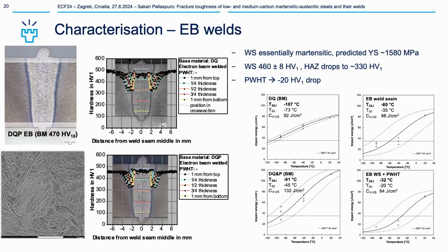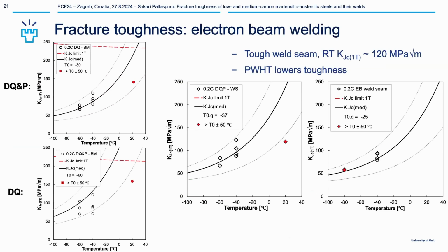Also for these electron beam welded materials, with environmental effects excluded, we see that properties are fairly in level with the hardness of the base material. So we achieved that there. Low mismatch, that's good. And there's also a good level of impact toughness. But when we look at the fracture toughness, from this level of minus 30 degrees or minus 60 degrees Celsius, we still get a provisional T0 of around minus 40 degrees Celsius. But we are still working a bit more to truly explain these low deformation properties.